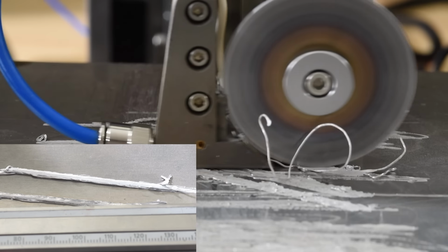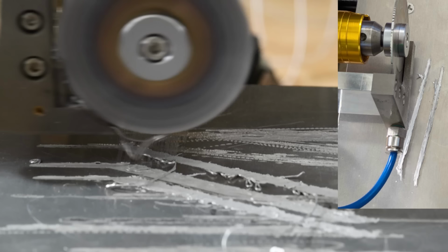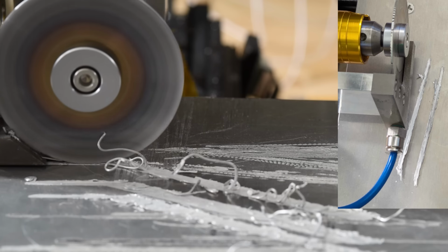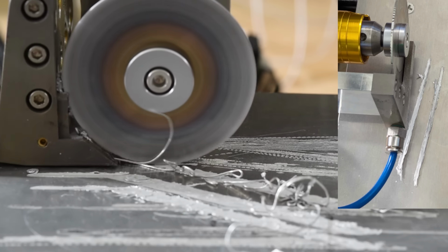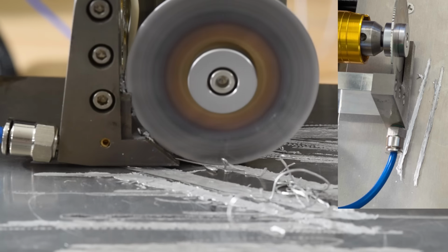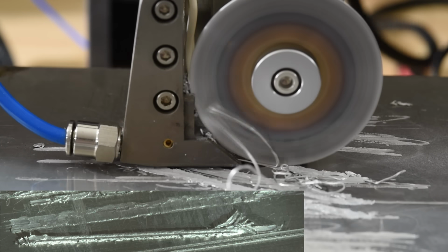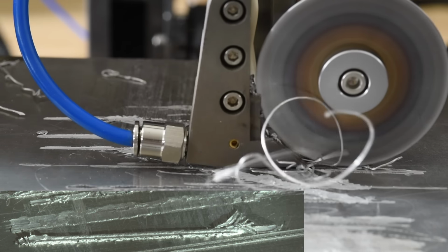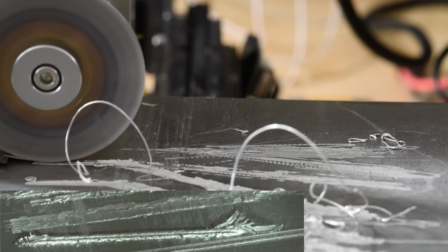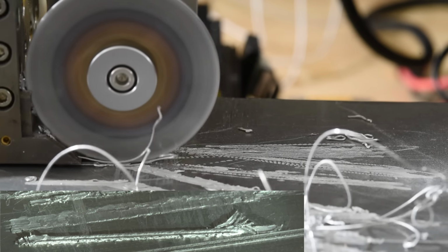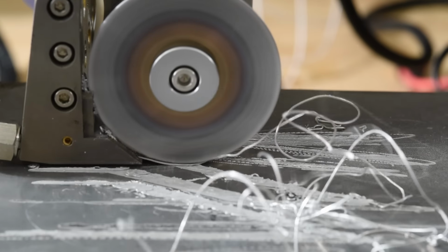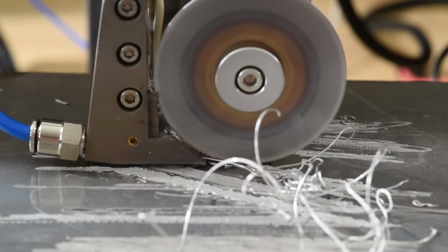And we started with angles from 1 all the way up to 22 degrees in order to test how well we could drift continuously. As you can see from the insets, angles from 1 to 22 turn out to be pretty good, but the background footage of us printing at 27 degrees shows that there are some serious limitations to the volumetric feed approach in keeping the wire under the wheel and keeping the deposits well defined.